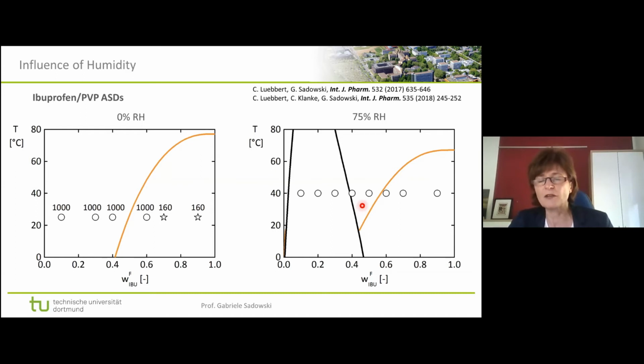And then we did our measurements, and this is the outcome of the measurements. What you see is that the demixing took place in a very, very short time. This is days again. So within the first day, we saw demixing in these samples. After 5 days, this sample crystallized, and then you see it took longer for the next and the next sample to crystallize. And these two samples here in the middle, they did not crystallize so far,